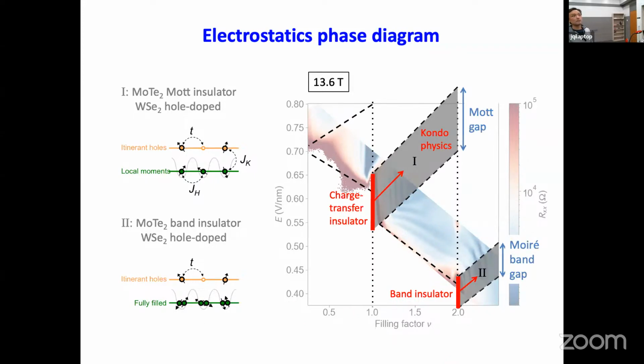And then finally, I just want to mention that this vertical span in the electric field really shows that the Mott gap and the Moiré band gap survive. That the Moiré band gap survives is not that surprising with doping in the tungsten, but the Mott gap survived also with the doping in the tungsten. And that really lays the foundation to realize the Kondo lattice physics.